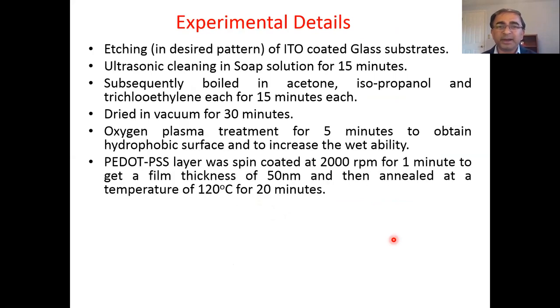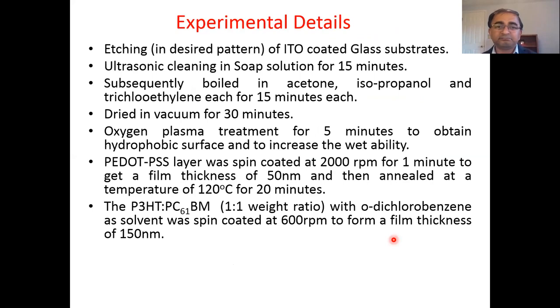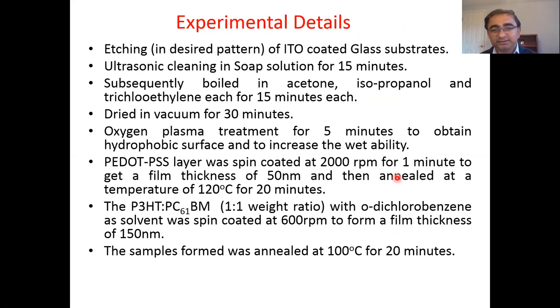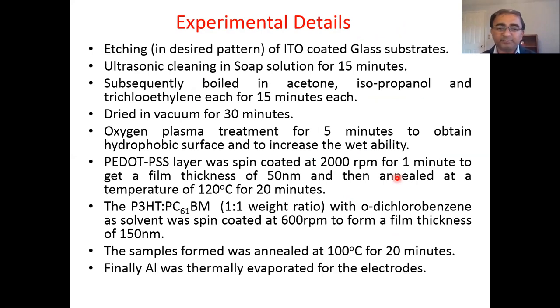Now experimental details. First of all, etching, then cleaning. There are different cleaning processes: oxygen plasma treatment for 5 minutes, then a thin PEDOT:PSS layer at 2000 RPM for 1 minute. These are all optimized parameters. And then 100 degrees centigrade for 20 minutes, the sample is annealed.